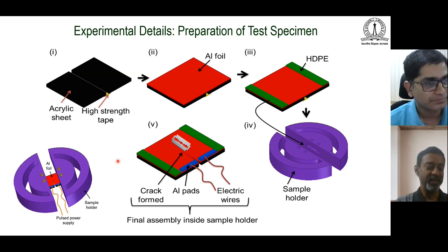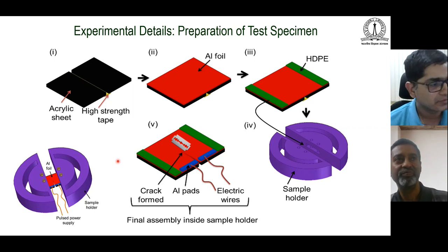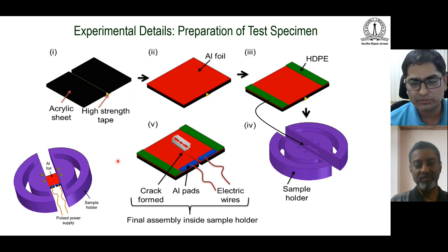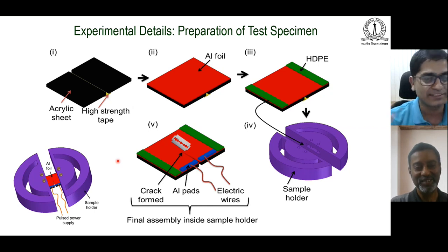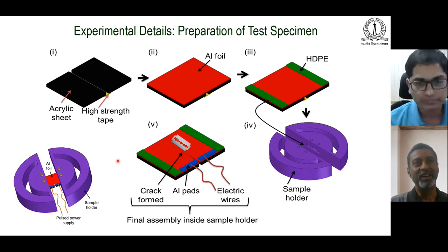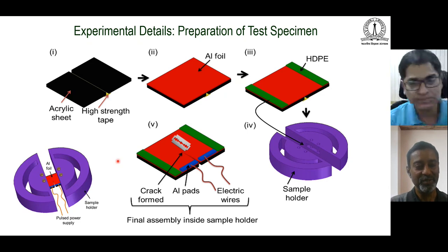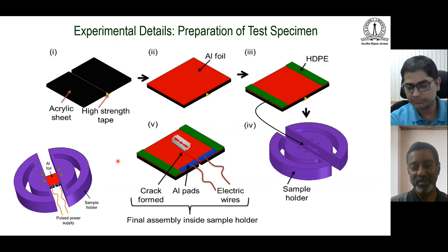So, yeah. What is the order of thickness of this foil? We have done experiments on 12 micrometers, then 20 micrometers, and now I think Swanand is doing about 50 micrometers thick foil, because we haven't been able to do the microstructure of this, and they are so thin. So now we are trying to increase the thickness to 50 micrometers, and hopefully we will be able to do some analysis. Yeah, that is what was striking me, because if you look at the grain size to the thickness, then the chances are that only about a grain is participating in each of your... That is true, it is only a grain, or a few grains, that is participating.